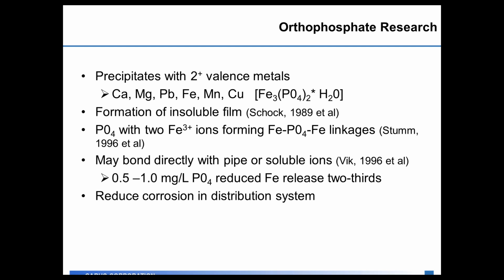As little as 1/2 part to 1 milligram per liter as orthophosphate reduces the amount of iron that releases from cast iron pipes by 2/3. But overall, the orthophosphate research shows that they reduce corrosion in the distribution system and would lower your lead and copper numbers and red water complaints.